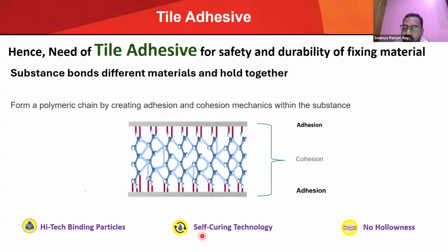Unlike cement or concrete, what happens? Cement or concrete somehow shrinks after 24 hours or after 12 hours. But tile adhesive will not shrink. At the time of application, the area it covers, it will cover the same area until the end. It will not shrink. So these are high-tech binding particles with self-curing technology, and that leads to no hollowness, of course, because it has good flowability and is thixotropic in nature.